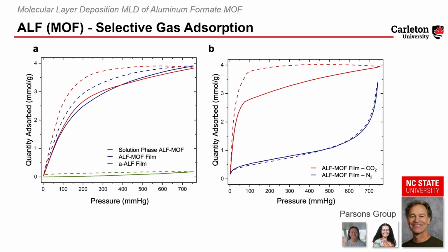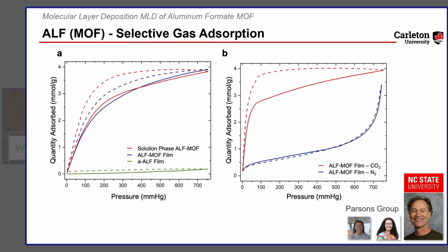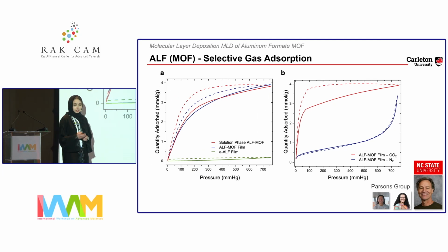Okay, and we know this MOF doesn't like nitrogen. So you try to do a nitrogen adsorption here versus the carbon dioxide. Nitrogen is a trace amount, and then carbon dioxide is very high, as expected, at 4 millimole per gram. I call that a success. I don't know what you call it.